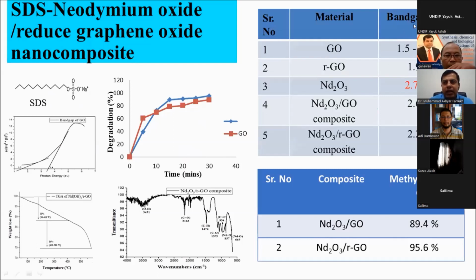This is another example, sodium dodecyl sulfate, an anionic surfactant. Previously we prepared neodymium oxide alone by using different plants. Here we are doping this neodymium oxide with graphene oxide and reduced graphene oxide. When prepared with graphene oxide or reduced graphene oxide, the band gap is reduced and its percentage degradation against different dyes is also increased. So this is the role of the surfactant.